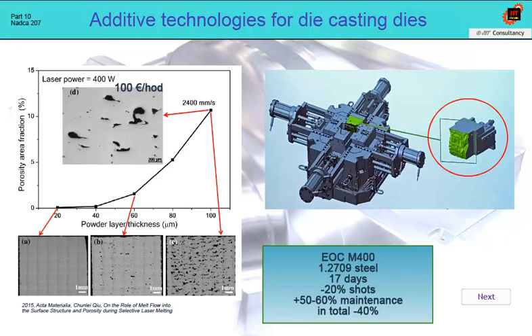The life of the part decreased by 20%, and the repair costs in both the tool shop and foundry increased by 50 and 60% respectively. What does this imply? 3D printing may therefore not be a real economic advantage. And if it is to be, we must look for ways to accentuate these advantages. And since the cost of powder steel and printing is the main item, then we have to solve the printing cost with a suitable printing strategy in combination with the maximum values of thermal fatigue resistance.